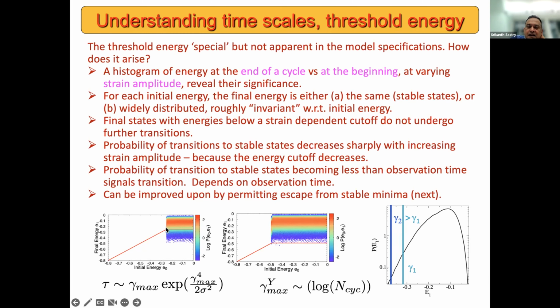Okay, so with this distribution, and also recognizing that out of these different energies that I reach at the end of a cycle, some states, which are the higher energy states, will undergo further transitions in the next cycle and the next cycle, whereas the ones that are below will not anymore undergo transitions because they're stable with the amplitude of deformation that I'm applying, I can then understand the result that I obtained for the time scale, the time it takes for me to reach a final state. And basically it has to do with the fact that as I apply larger and larger strain amplitudes, the number of states that are available that will be stable with respect to that amplitude is a drastically decreasing function. And as a result, the probability that I'll make a transition to one of those states in a given cycle is smaller and smaller. And therefore, it takes me a longer and longer time to reach a final state,